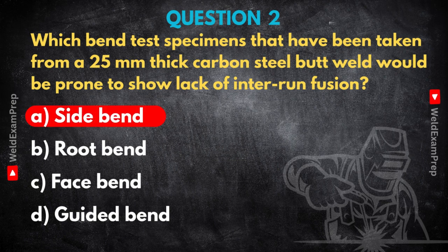Side bend. Why specifically the side bend for lack of interrun fusion in, well, fairly thick plate, like 25 millimeter? Okay, so first, what's the lack of interrun fusion? It's basically where 2 adjacent weld runs, or a run and the base metal, haven't properly melted and fused together. It's a gap, essentially, inside the weld. Like a hidden layer that didn't stick.